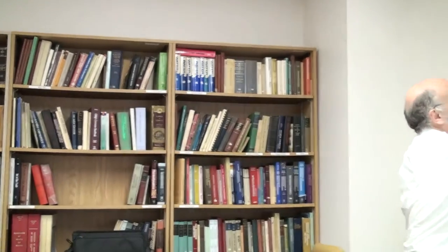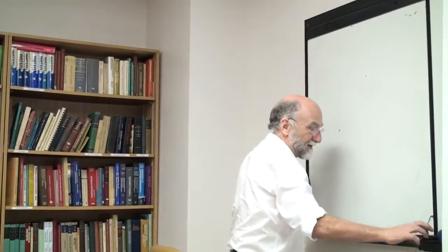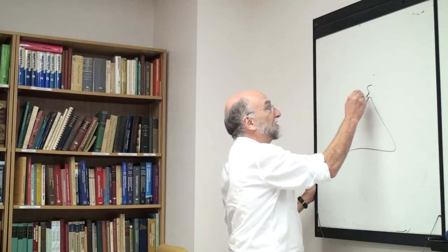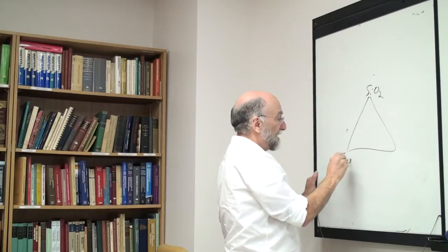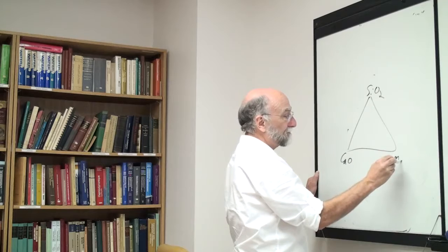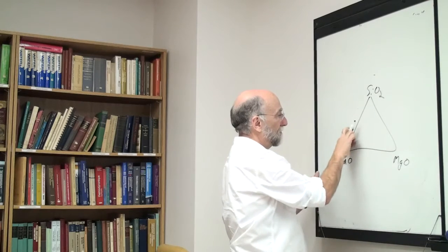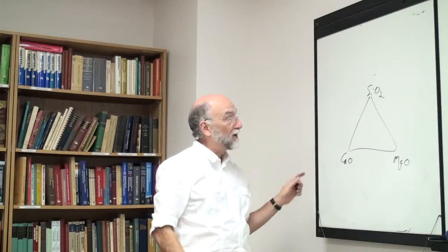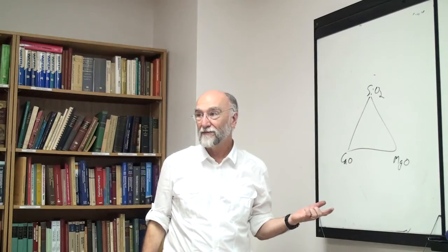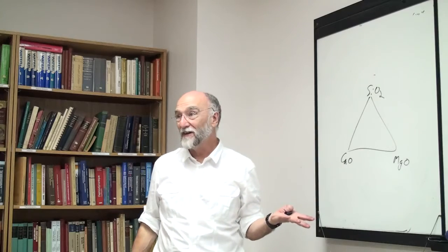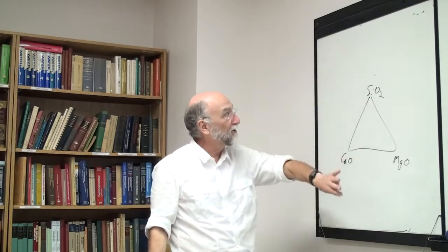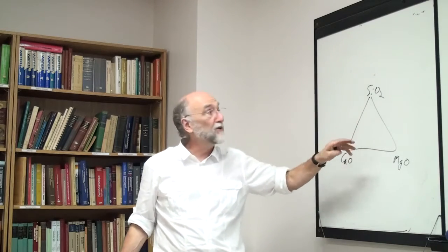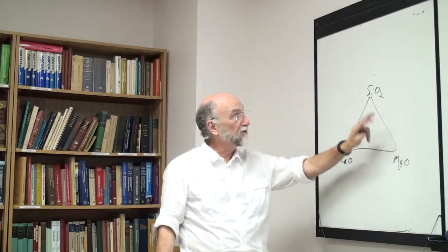You can now, there's not, well, okay, I see what. Maybe I wasn't quite right. There are cases where you don't know. Let's say you take SiO2, CaO, MgO. That is already a quasi-ternary section in a four-component system, all right? So now we're in a quasi-ternary. A quasi-ternary, all tie lines lie on that. There's nothing that goes outside that plane. Calcium's always 2+, magnesium's 2+, silicon.